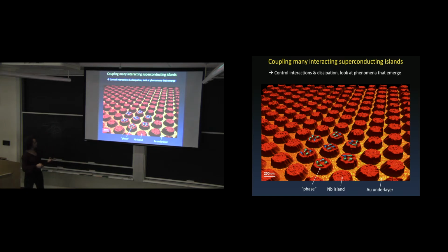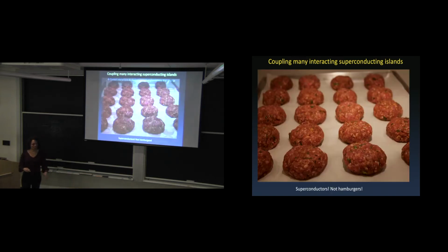So this is an actual AFM of the devices that we made. These are niobium islands on top of gold. And niobium is superconducting, the gold is not until they're coupled over some distance, and then we drew in the arrows to represent phase. Okay, so we use these systems to control their interactions, and look at the phenomena that emerge in that case.